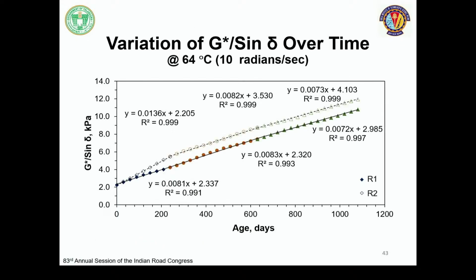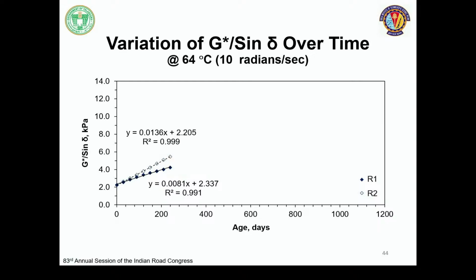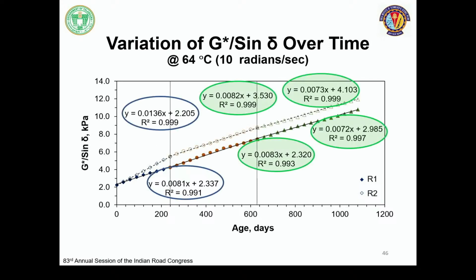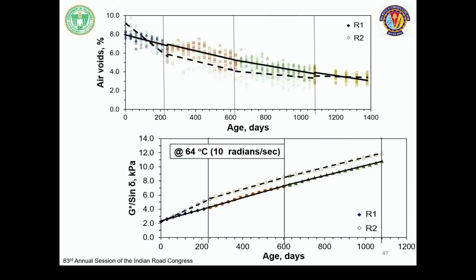Yeah. So we tried to find the G* by sin delta. That is one parameter that has to be verified. So we chose G* by sin delta as a parameter to find what is the stiffness variation with respect to time. We found a similar trend where the initial stiffness was quite high and later on it became linear with respect to R1 and R2. So there was not much variation. Even here we split into 200 days and tested. Yeah, initially there was variation and later on it showed a similar trend.